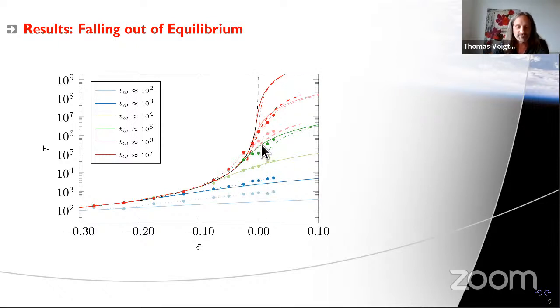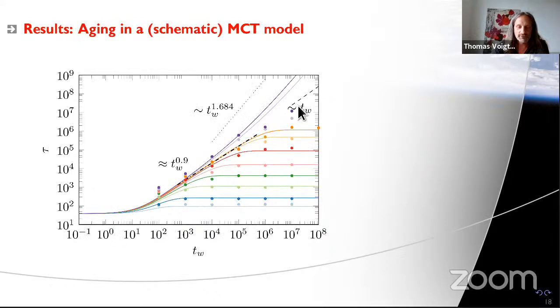And of course, qualitatively, it's very tempting to say that we have a better theory now, because we have a point where the relaxation time would diverge if we waited infinitely long. And you would argue that this is a packing fraction just above phi g and not phi c. However, I would argue that these 4 points that I was mentioning here before tell us a more interesting story.